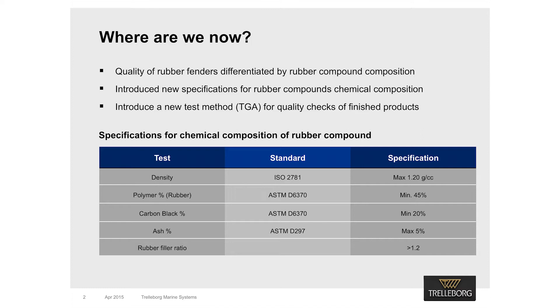70-80% of a typical rubber fender's formulation consists of raw rubbers and carbon black, while the remaining 20-30% consists of 10-15 other small ingredients. Raw rubbers could be natural or synthetic. A fender cannot be produced directly from raw rubbers. Raw rubbers, carbon black and other ingredients need to be converted to a rubber compound via a mixing process. Rubber compounds are then converted to a fender by molding, extrusion or wrapping process.